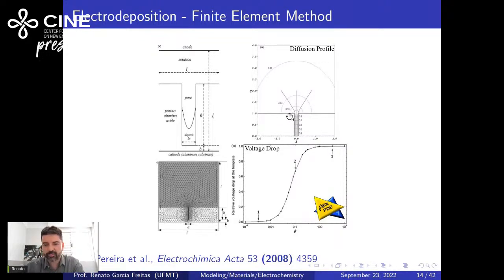If you take a look at this part, the top of the bottom of the tube, even from the bottom here, we can divide in three parts, the 3, 2, and 1. And take a look in this part here, we have the relative voltage drop. The voltage drop concerns three parts, the top and the bottom. And we have in the top, the unity of the voltage drop, as you see this part, 3. In the middle of the tube, or in the pores, for example, we have this part, and in the bottom, we have this part for relative voltage drop. That's the main explanation. That's the reason it's very difficult to deposit something inside the nanotubes, or in this case, aluminum inside the nanopores as well, and we need to use a pulsed kind of technique.